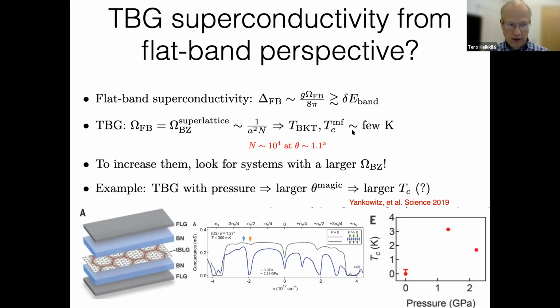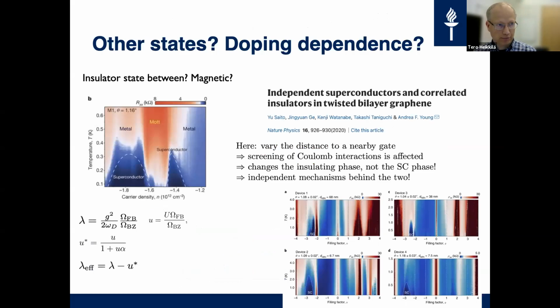So the message here is that to increase the TC in these systems, you should look for systems that have a larger Brillouin zone, or larger flat band area. This was actually done in one experiment where they applied pressure on this bilayer graphene, and this way they could find the flat band at a much higher magic angle, which actually led to a larger TC. So this is consistent with this picture.